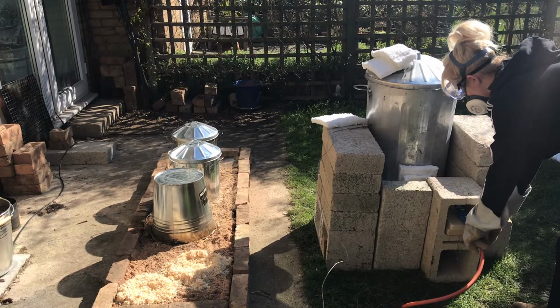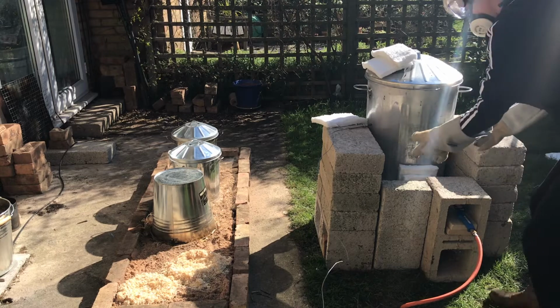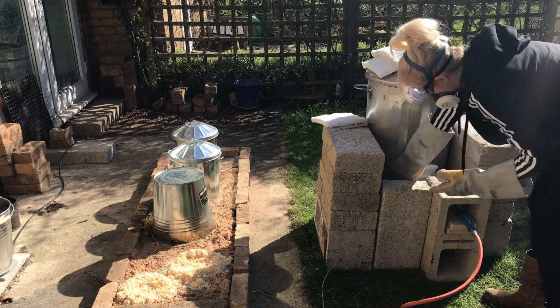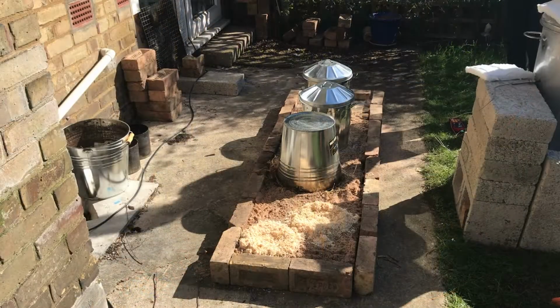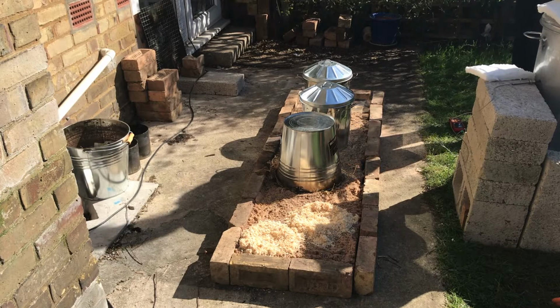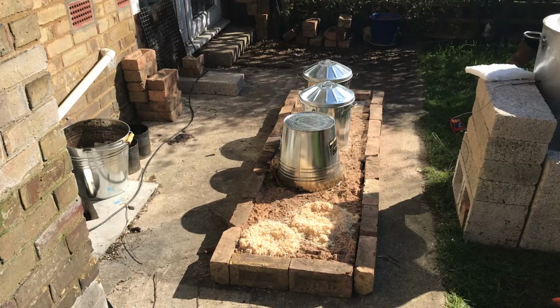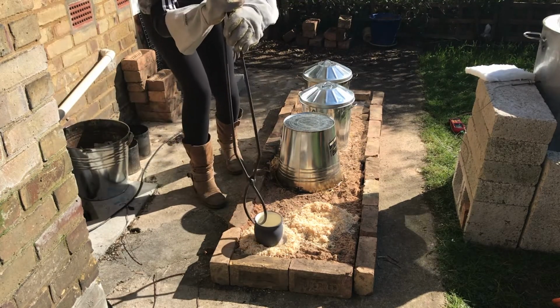And I let the kiln cool now to 760 degrees centigrade. That just starts off the reduction process. It takes maybe about 5 minutes for it to drop to 760 degrees centigrade. And when it's done that, I lift the pots out of the Raku kiln. I carry them over to the sawdust area.